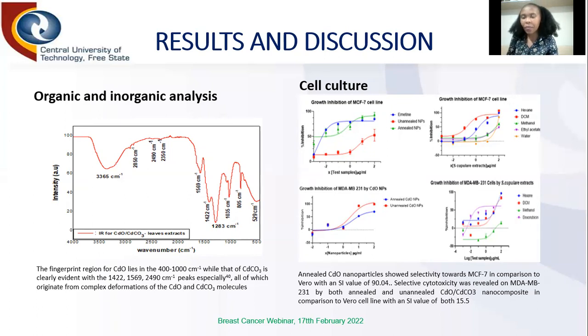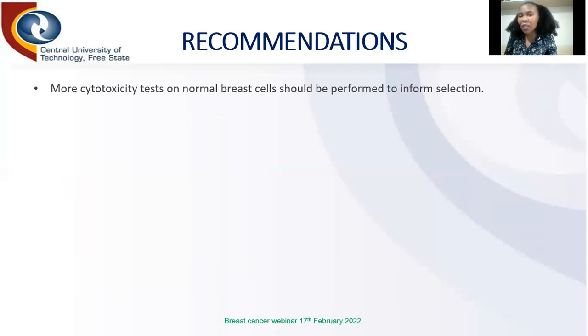And secondly, the MDA-MB-231 cadmium oxide nanoparticles, both annealed and unannealed, showed a selectivity index value of 15.5, which is relatively a good selectivity index. And also this shows that indeed cadmium oxide, cadmium carbonate nanocomposite are selective towards breast cancer cells. However, I would recommend that moving forward, more cytotoxicity tests on normal breast cells should be performed to inform selection.